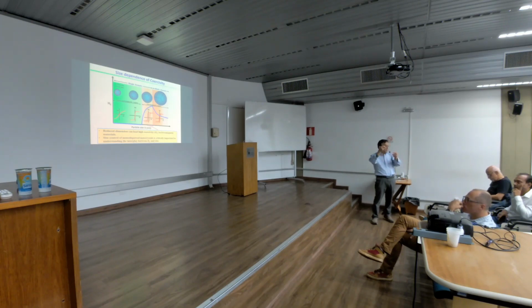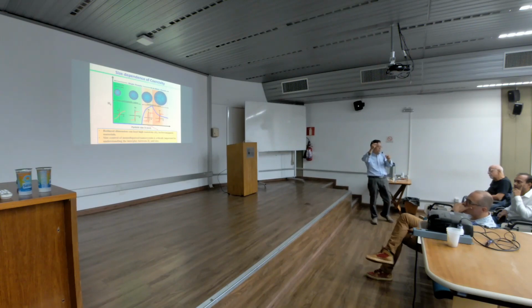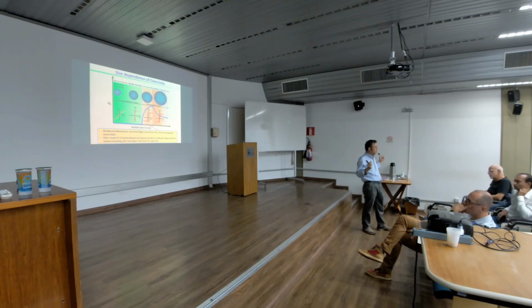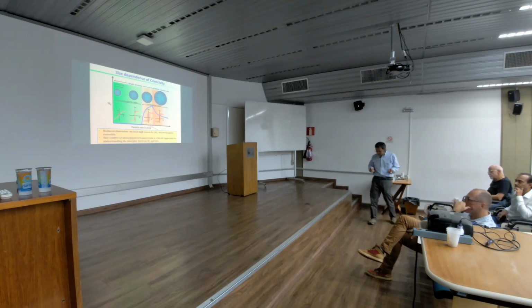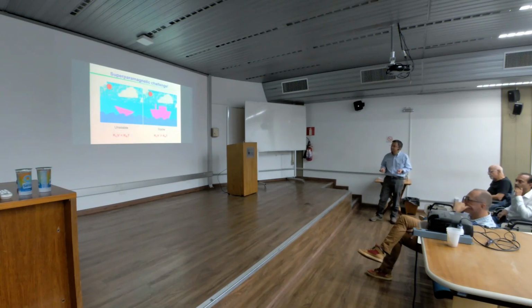We want the recording density higher and higher. That means you have to reduce the bit size smaller and smaller. But then you meet the superparamagnetic barrier. You hit it and stop. So in order to do this, we have to have a good understanding of why superparamagnetism takes place, which is actually simple. The formula is: the anisotropy constant of the material times the volume, KV, is large compared to the Boltzmann constant times temperature, kT, because the thermal fluctuation increases with temperature.